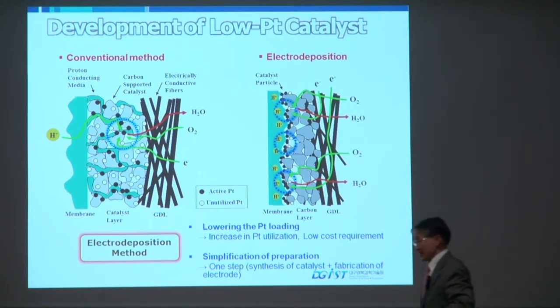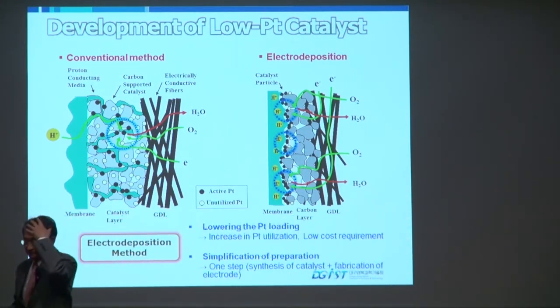And the second part is, after you deposit your platinum, it tends to be amorphous in nature. The catalytic activity is very low. So you need to heat this catalyst to about 250 to 300 degrees to have a reasonable crystallinity of this catalyst. But when you have this in Nafion, Nafion cannot stand more than 120, 130 degrees. So there are two problems. So we have to solve these two problems.